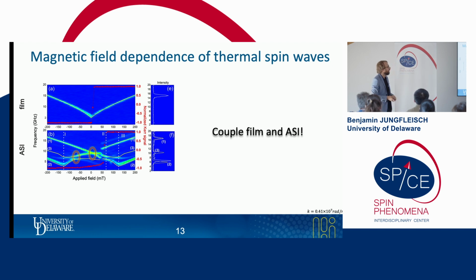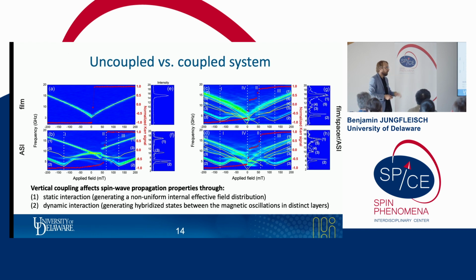Now let's couple our film to the artificial spin-ice system. So this is the overview. This is what we get, and I'm going to explain this in more detail in a moment. The take-home messages are that the vertical coupling affects the spin wave propagation properties in 2 different ways. The first one is the static interaction, generating a non-uniform internal effective field distribution. And the second one is a new form of interaction, the dynamic interaction, generating a hybridized state between the magnetization oscillations in the top and in the bottom layer. So this is the take-home message.